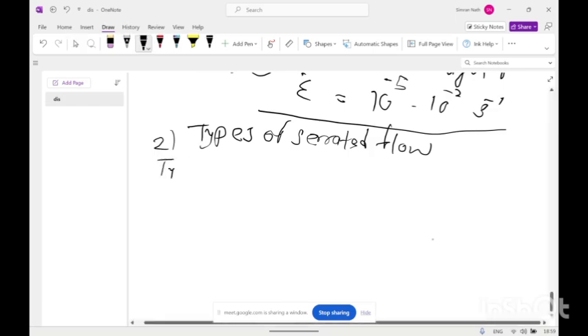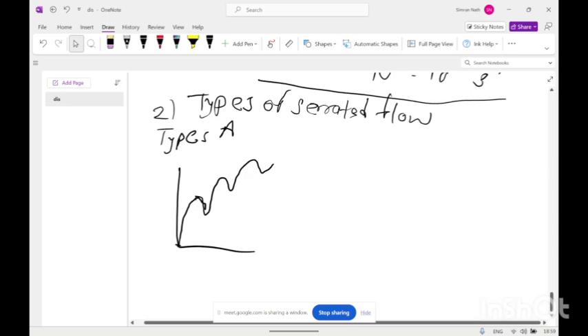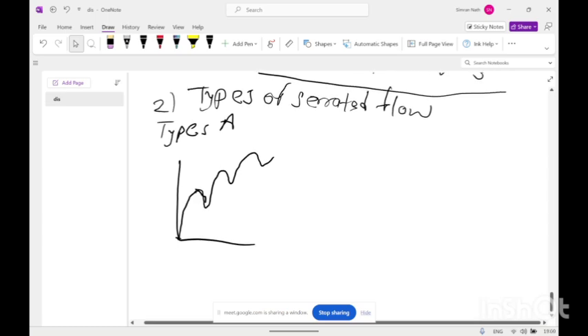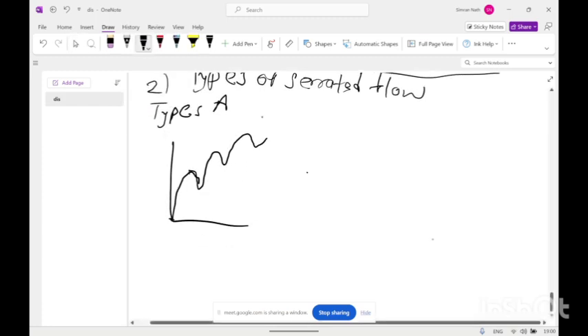So in the type A, so there are three types of serrated flow. Like in type A, there is a step by step increase in the stress. This increase in A describes that the deformation bands move continuously through the gauge length, and the humps and valleys correspond to the disappearance of a band and initiation of a new band.